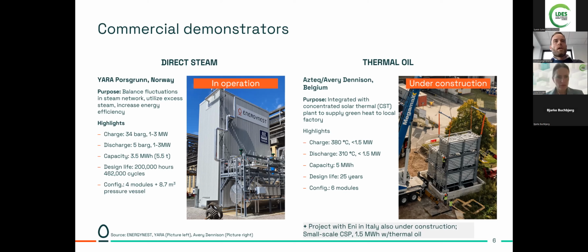In this system, we have 4 modules combined with a pressure vessel. We also have our own patented design for the functionality of the steam solution. And in this small plant, which is only 4 modules, we have approximately 3.5 megawatt hours, but we can discharge at a power of up to as much as 3 megawatts. And this is for short-term load fluctuations in the steam network. You see that we have designed this for 200,000 hours of operation and almost 500,000 cycles.